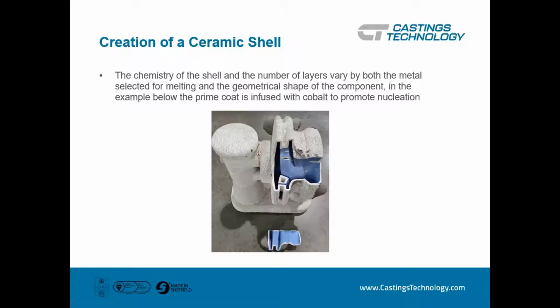The reason that's blue inside is that the prime coat, which is the first coat you put on the model, is the most important one. It's the most expensive. It's the one that's the KFC recipe that nobody gets to know about, because that's where all the technology is. That is the coat that's going to see the incoming metal stream, which is going to be significantly hotter and heavy as it splashes into the shell. This particular one is blue because it has cobalt in it. Cobalt helps to promote nucleation on certain materials, but it gives you an idea of what a ceramic shell actually looks like.